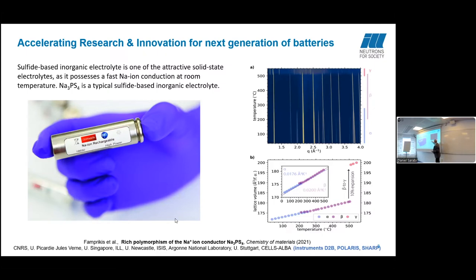This is Q, and these are Bragg reflections as a function of temperature. And what they saw was that there's an alpha phase that's stable up until about 250 centigrade. And then there's a slow second order transition to a beta phase. And then finally, right at the top, at about 500 Celsius, there's a very abrupt first order transition to a gamma phase. It's still crystalline, but it has very little long-range order.